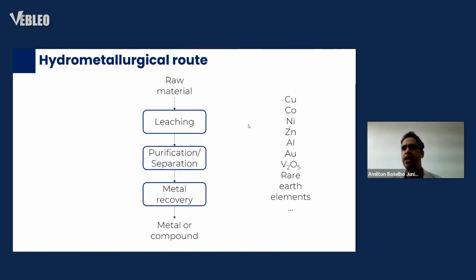Then, after the leaching step, purification and separation steps are required to obtain different products. For example, a copper concentrate solution, or cobalt, nickel, aluminum, gold, vanadium, rare earth elements, to obtain a rich solution of these separated elements, and then to obtain the product: the metal, for example metallic copper, or a compound, which can be cobalt sulfate, nickel oxide, nickel carbonate, and so on. That depends. With the hydrometallurgical route, the main advantage is making it possible to have small companies spread around the country. So that's the main reason.